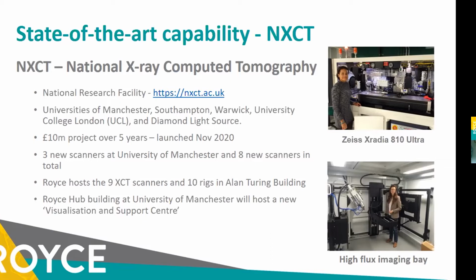So our NXCT hub is based at the University of Manchester, and Royce hosts all of the XCT scanners at Manchester, where we have both cabinet-based systems and also walk-in bays. We've got a range of testing rigs that allow us to do both ex situ and in situ testing. Our systems cover a range of imaging resolutions, voxel size from 50 nanometers up to 1 millimeter for specimens ranging from 65 microns to 1 meter in length and diameter.